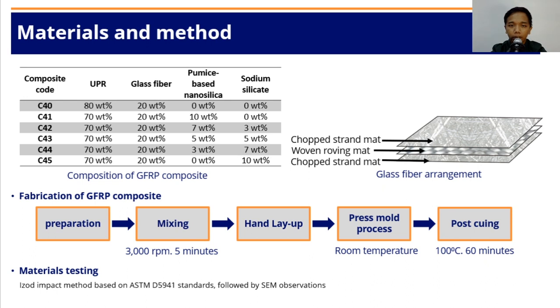The first is the C40 composite, which is a composite without the use of filler. The second is composite C41, which is a composite containing 10% pumice-based nanosilica without sodium silicate. The C42 composite is a composite containing 7% pumice-based nanosilica and 3% sodium silicate. The C43 composite is a composite containing 5% pumice-based nanosilica and 5% sodium silicate.